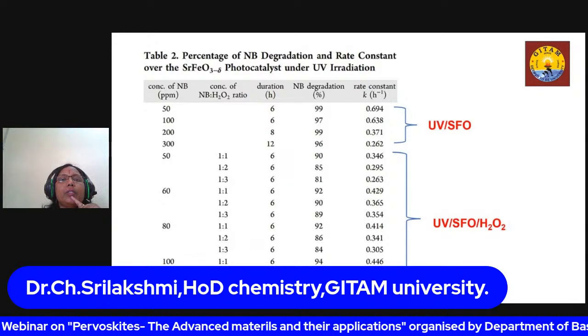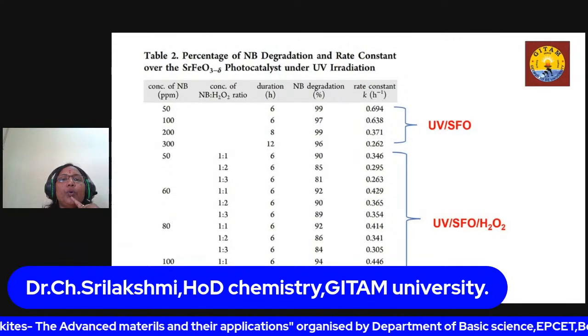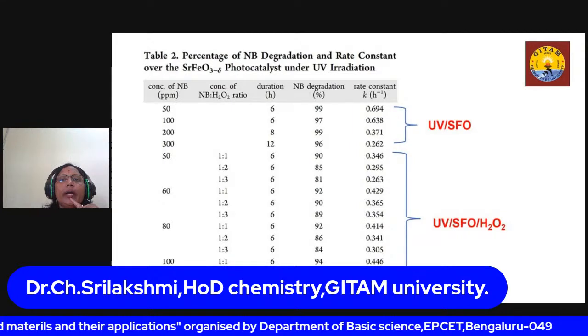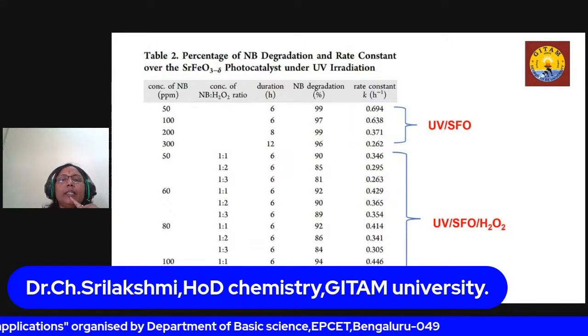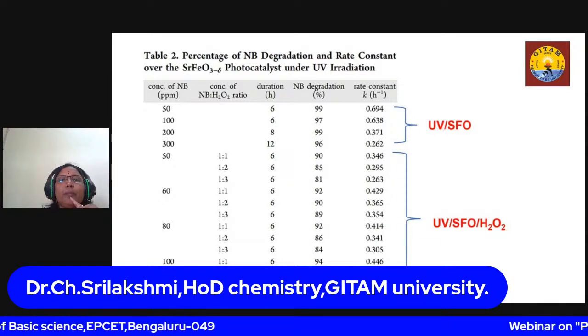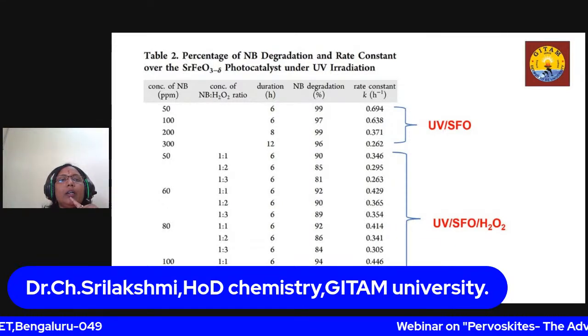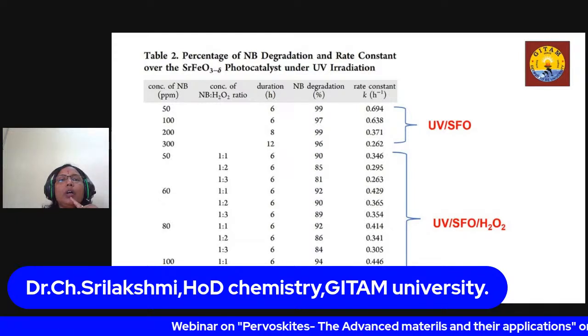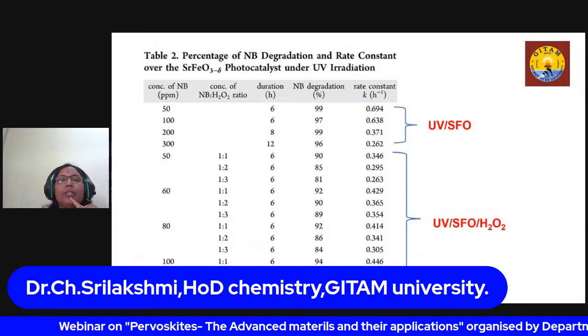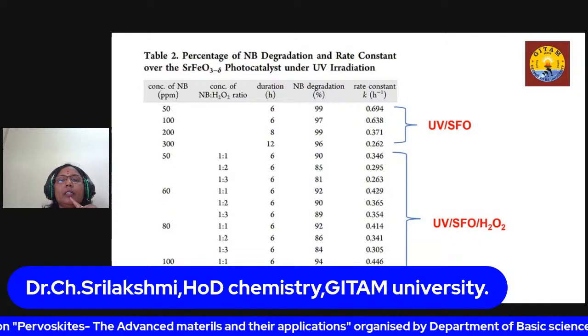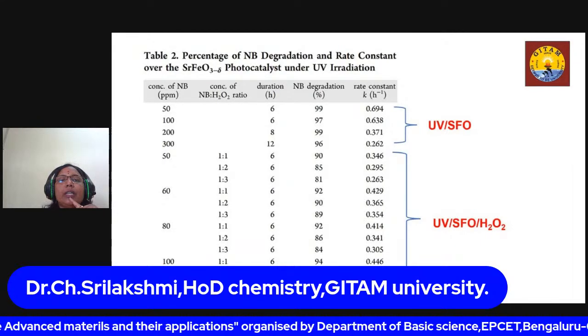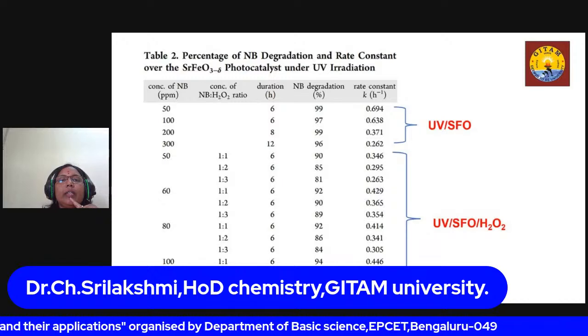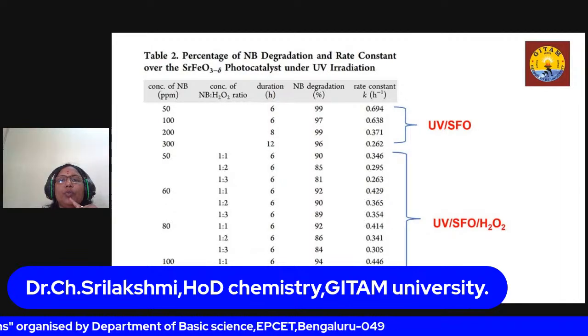from low to high concentration without using H2O2, it just degraded in low time, from 99 to 96, and the rate constant is also good compared to the degradation using H2O2 for nitrobenzene degradation. So with 1:1, the rate constant is 0.346. It goes down to 0.29 when I increase the molar ratio of H2O2, and it further goes down like this.